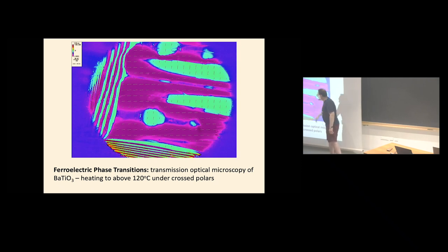However, when it goes through the crystal, and if the crystal has an anisotropic optical indicatrix, then there are magical things that go on. So in order to obey Maxwell's equations, the light must split into 2 different parts generally. And in these crystals, there is a speed difference between the 2 parts. So when they recombine, there's an effective polar rotation. And that gives you these beautiful colors.